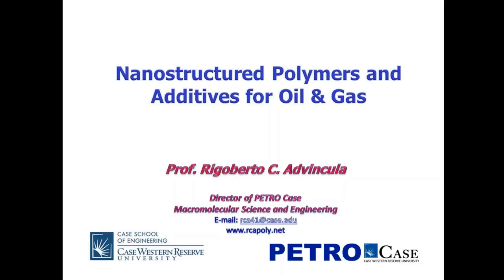And because of the smoothness of the films that we're working on, the high hermetic sealing or barrier property between the carbon steel and the produced fluid, we have advantages over some of the epoxy and urethane systems that have been tried as internal coatings.